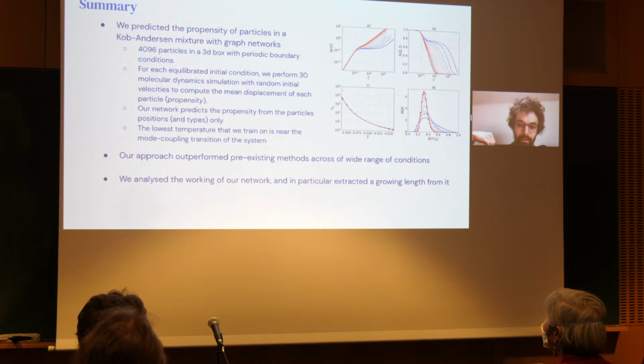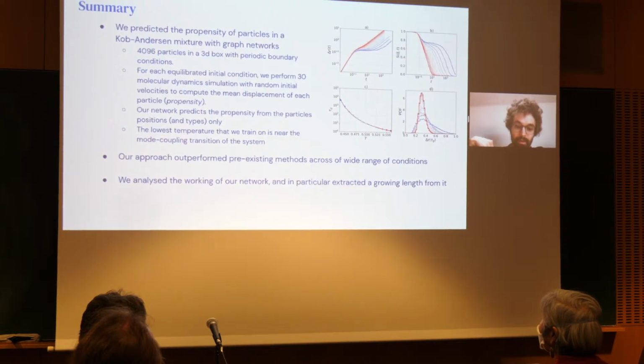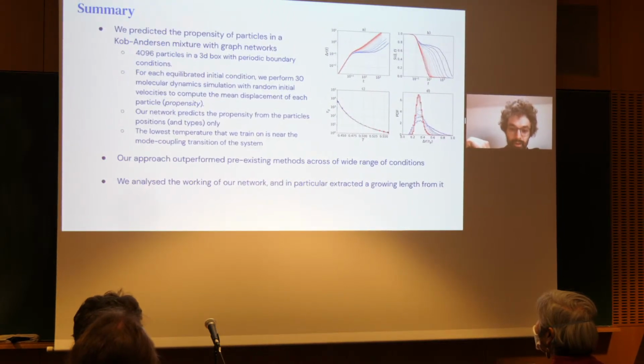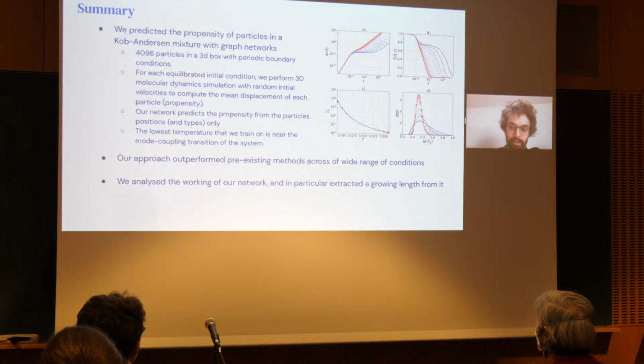And we went to temperatures close to the mode coupling temperature of the system. What we showed in this work is that the approach outperformed the existing methods at the time over a wide range of conditions. And we also tried to do some work on analyzing the workings of the networks and extracting knowledge from it.